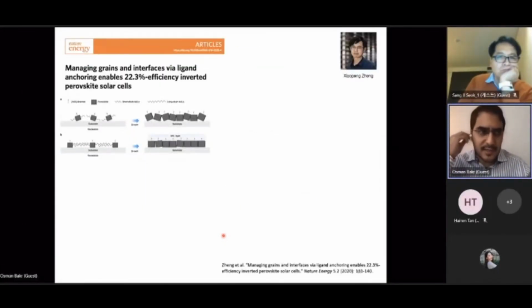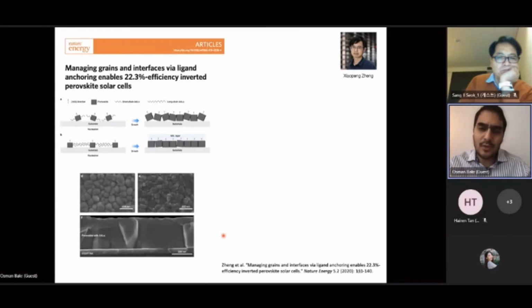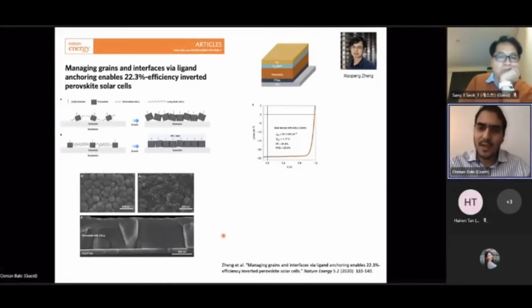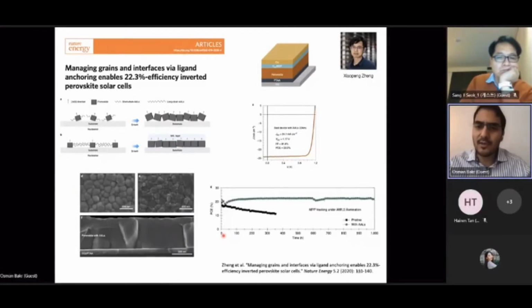But we were also inspired by these ideas of ligand exchange and using alkyl ammonium ligands. We started looking at whether we can apply this to perovskite thin films. We looked at short and long chain alkyl ammonium ligands, and we found that when you used trace amounts of short chain and long chain alkyl ammonium ligands, you could control the nucleation of the perovskite film and the orientation of the perovskite, and you could also stabilize the surface and improve the stability of the material quite a bit. We were able to obtain, at the time, a record for p-i-n type inverted solar cells. And it just showed us that there are a lot of concepts from nanocrystals that could be useful for solar cells.